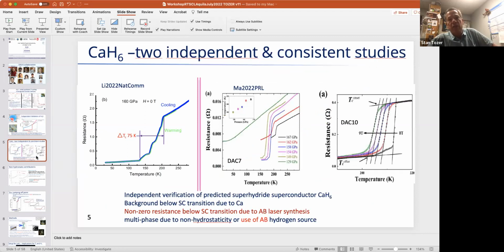And then recently there were two very nice studies of CaH6, completely independent studies and completely consistent results, one by Li and one by Ma. We heard from Ma yesterday, and beautiful talk and extraordinary results, both theoretical and experimental. But you can see with Li, he has a multi-phase transition, which is typical for when one uses AB. And also there's background below TC that is non-zero. If you extend far enough, you're not going to get to zero with this material.